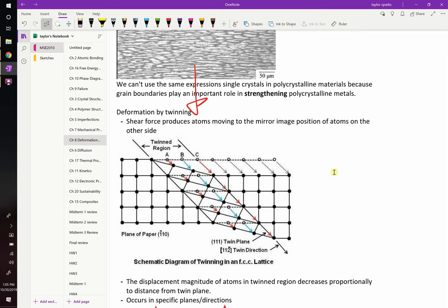What we're going to expect to see is at low temperature, when I bent that thing, you could hear the crunching, crackling noise, and that's twins. You're literally hearing twins form. That's the way that it's deforming. At a higher temperature range, there's no reason to believe that the same deformation mechanism will hold over all temperature ranges.